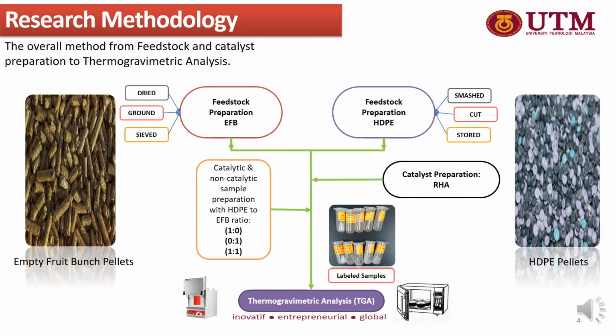In order to execute a proper experiment, a relevant methodology was created. Firstly, both feedstocks, which are the EFB and HDPE, were prepared by almost similar steps of drying, grinding or smashing, and stored in separate containers. Both feeds were stored in powdered form. Six different samples with different mass loading ratios of EFB and HDPE were prepared, where three of them are non-catalytic and the other three are catalytic samples with the presence of the synthesized and characterized rice husk ash catalyst. Then all six samples were sent to thermogravimetric analysis to investigate the effect of mass loading ratio in co-pyrolysis over rice husk ash catalyst.